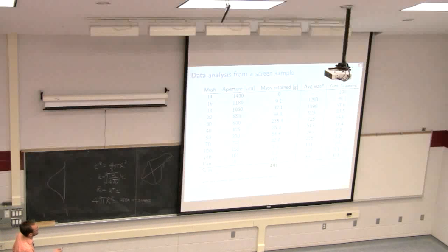There's a whole distribution of them. There's particles that are much larger and particles that are very, very small. So some things to be aware of when you're doing this: you should almost always have a zero mass retained on that first screen. It's good practice that you put a screen at the top through which all your particles will pass. Okay? Because if you don't have that zero at the beginning, then you're going to get mass landing up on that next screen that really should have been on that prior screen. So you might bias your results by having a greater weight over there or greater mass over there than should otherwise be there. So it's good practice to keep adding screens until your first screen gets you a zero.